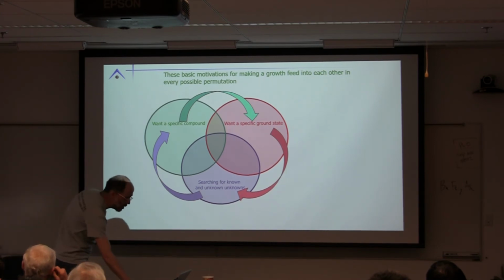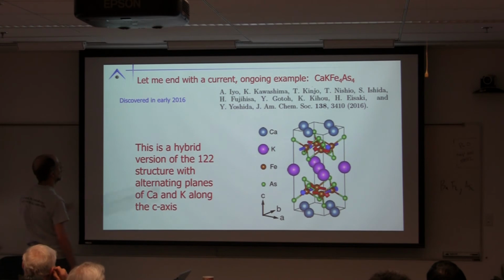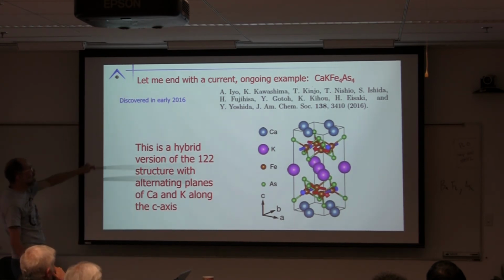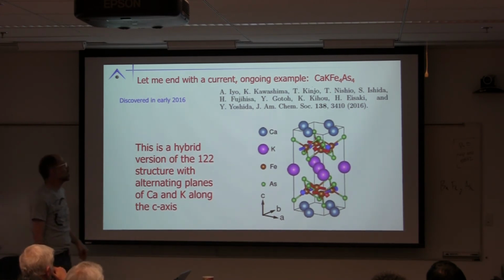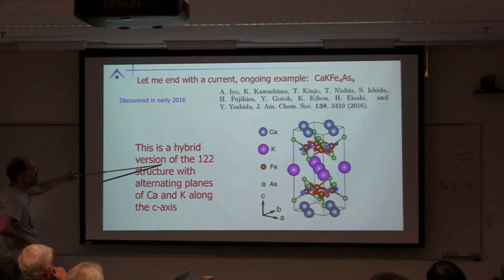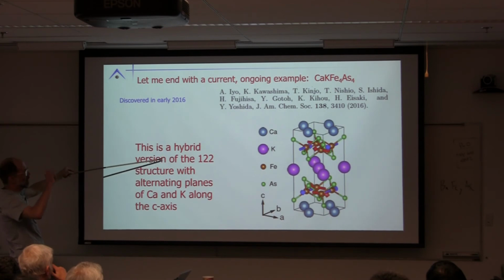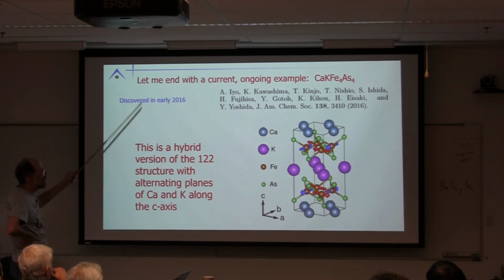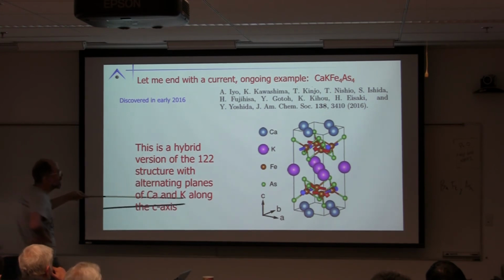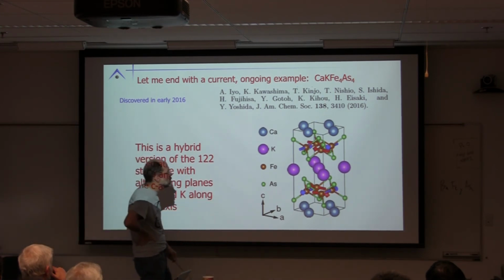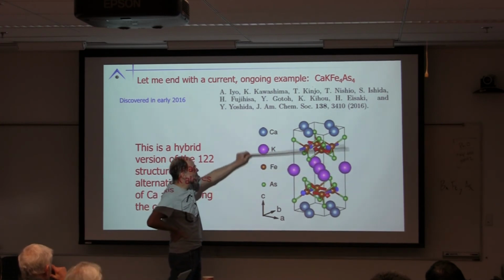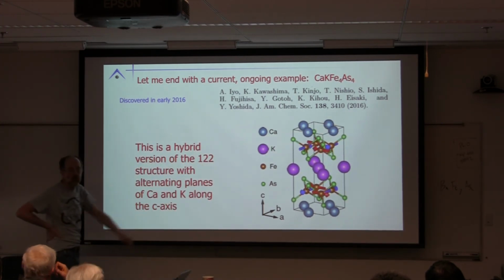Let me end with a highly contemporary example. Okay? This is still ongoing. I don't have the end of the story, but calcium, potassium, iron 4, arsenic 4 was discovered in early 2016. Okay? This is a hybrid of the 122 structure. There's enough contrast between the sort of C lattice parameters between calcium iron 2 arsenic 2 and potassium iron 2 arsenic 2 that when you put them together, they actually prefer to segregate into separate potassium and calcium layers. So it forms a true quaternary.